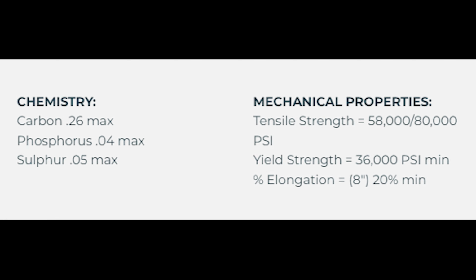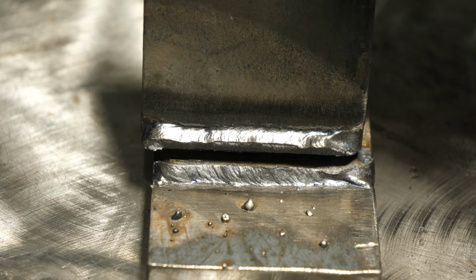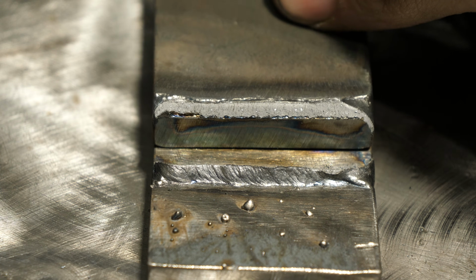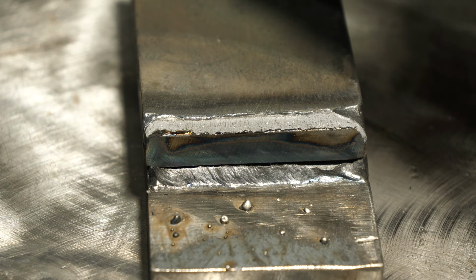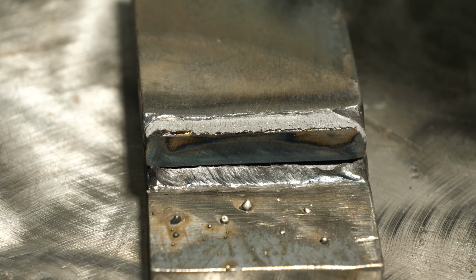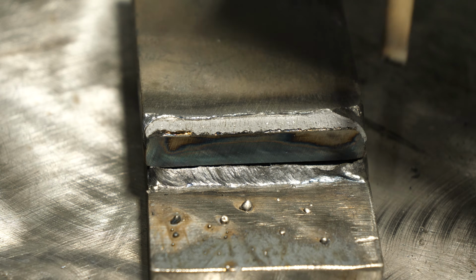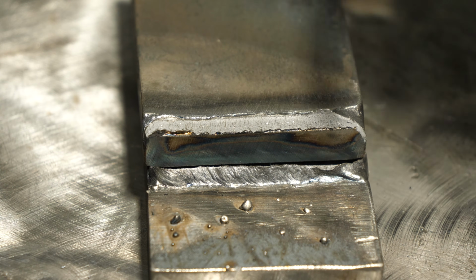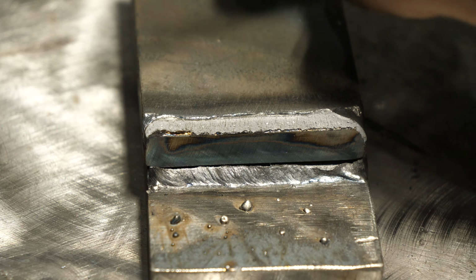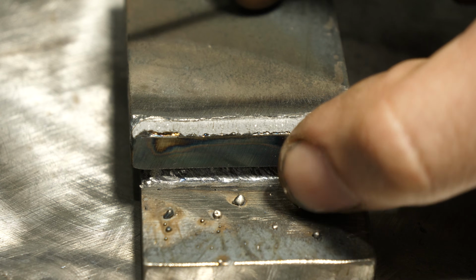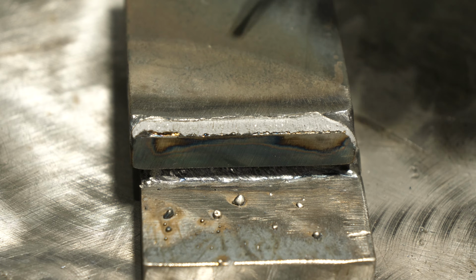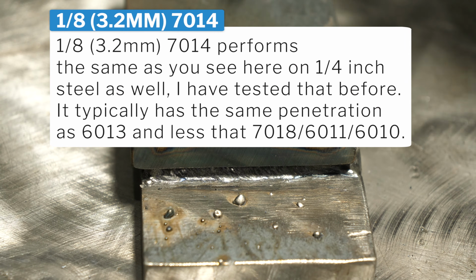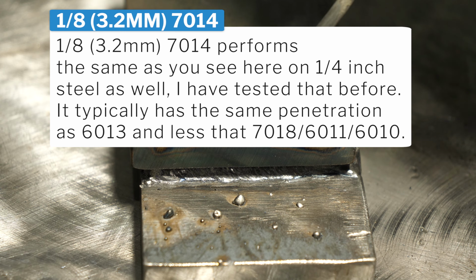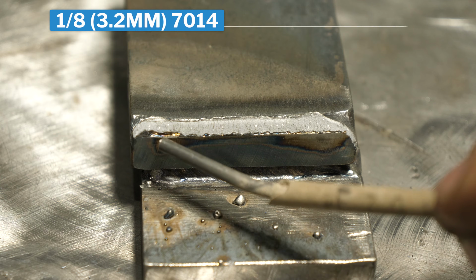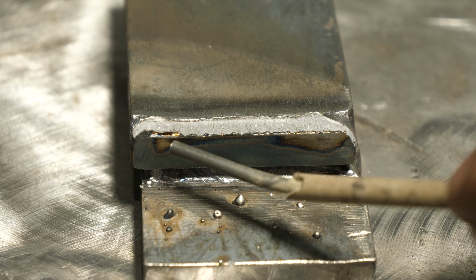All right, let's move on. So as expected, this broke. They always break on this. And the results are a little bit lackluster, and that's somewhat, I guess, what I expected. So this broke at sub 50, which is very similar to the 6013 weld. And the primary reason behind that is that 7014 really doesn't have much penetration. And anytime you bend something towards the face of a weld, if there isn't penetration, you're going to have far poorer numbers.